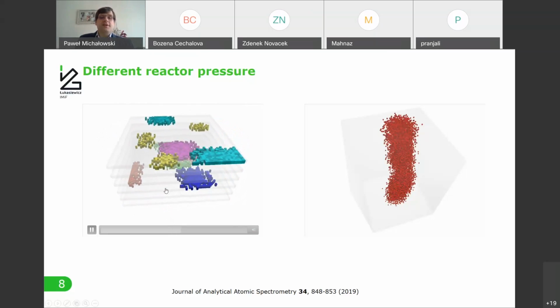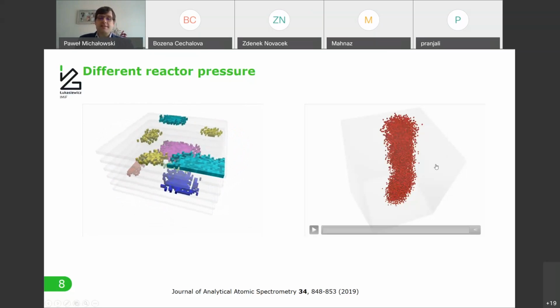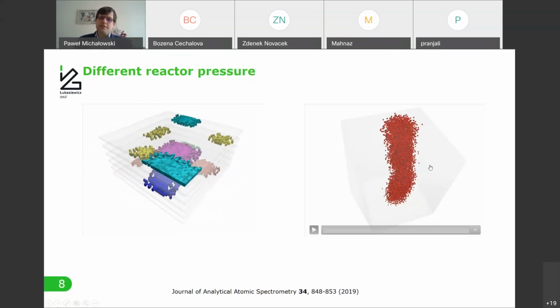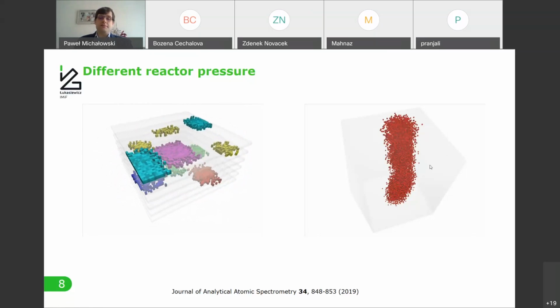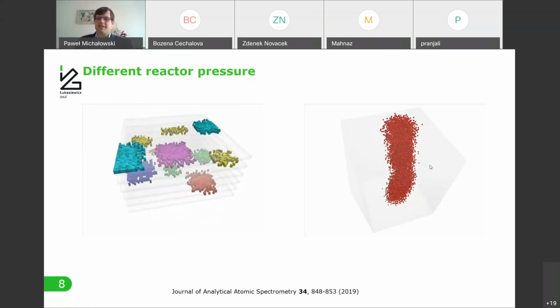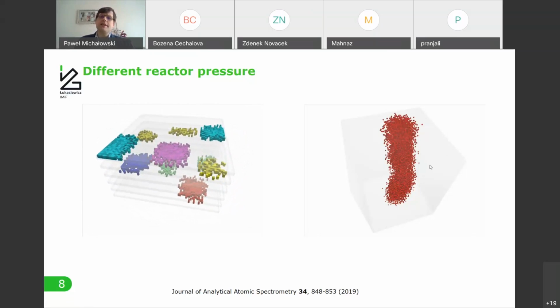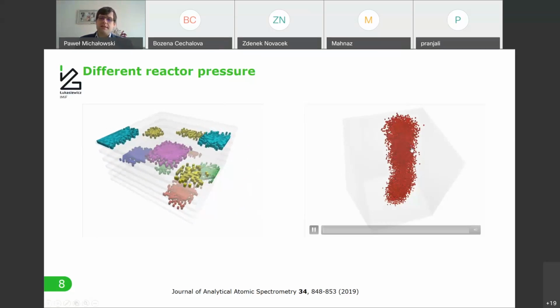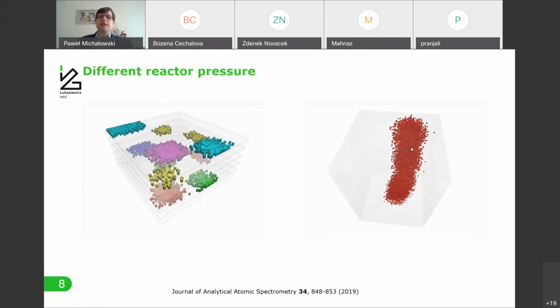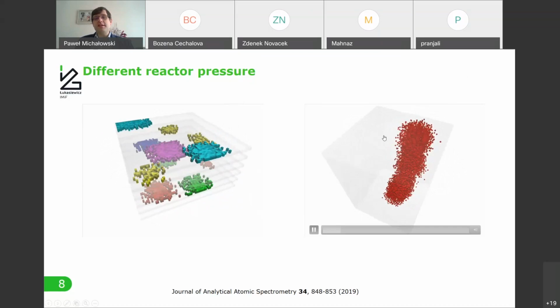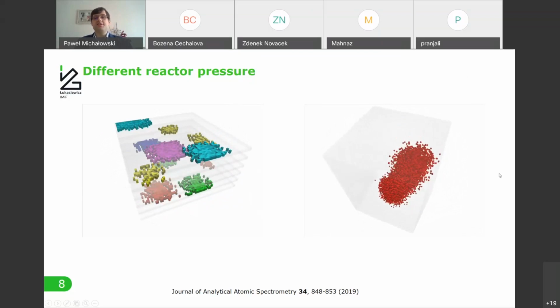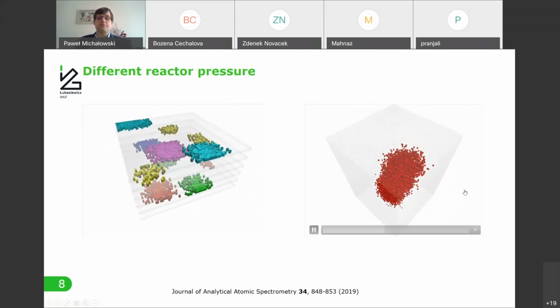On the other hand, for a low reactor pressure on the right-hand side, first of all, we can grow as many boron nitride layers as we want. So here there are 66, I think, layers. But more importantly, you can see that the correlation of the position of precipitates in one layer to the layers underneath is very good. So here we can see some kind of pillar-shaped structures of carbon. So there is a pretty strong difference between these two growth modes. So we made a conclusion about it.